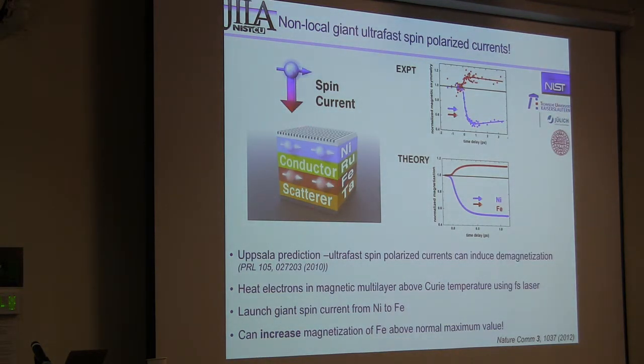So we take our magnetic multilayer, heat all of the multilayer with a femtosecond laser, and then read out how fast the magnetic state in the nickel and iron change. The magnetization in the nickel layer decreased, which is what we expected, since if you heat the electrons above the Curie temperature, you're supposed to see the magnetization disappear. But what was surprising to us was that the magnetization in iron increased above its normal maximum value. And there's no way you can explain that if spins are not moving between nickel and iron, because we weren't doing anything to increase the magnetic moment in iron.